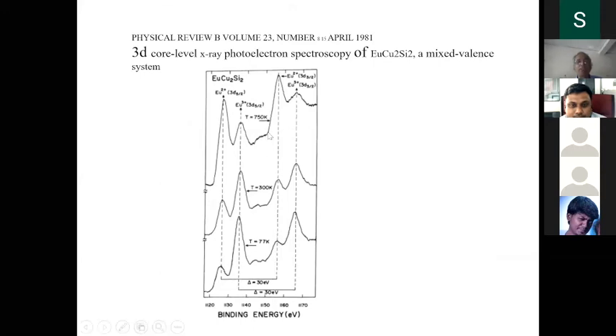Europium is the core level. I already showed you the 4f valence band. Here, you can look at the core level, and you will see the core level spectroscopy also shows signatures of both valence states if there is intermediate valence. Here is a compound as a function of temperature, published in Physical Review Rapid Communications in those days. You can see one valence state, 2 plus, and another valence state, 3 plus. These are spin-orbit split.